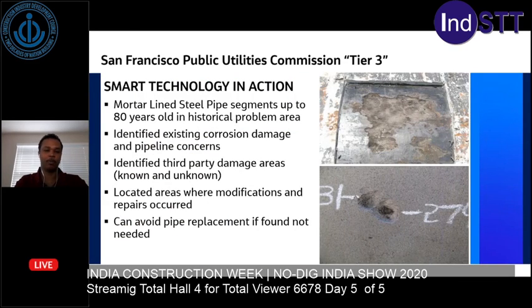And as Margaret mentioned, some of the pipelines were up to 80 years old, typically in a historically problematic area. Again, it pinpointed that corrosion damage, and also identified some of the third-party damage areas that occurred, those that were known and those that were unknown. And we were also able to locate modifications they may have made within the system in the past, and repairs that may have happened on the line that they didn't have records for. And you can make a decision based off of the MFL tool to see if you want to do just a replacement, maybe a cutout, or just a simple repair based on the results of the MFL tool. Next slide.